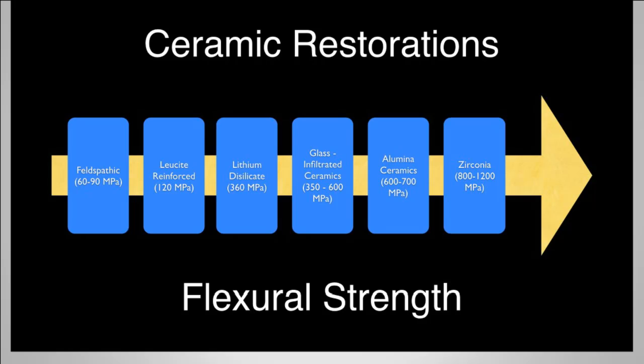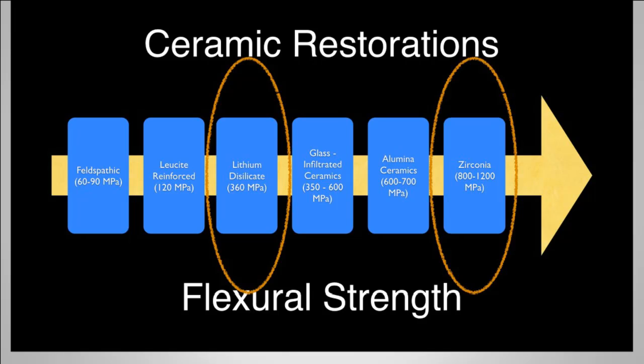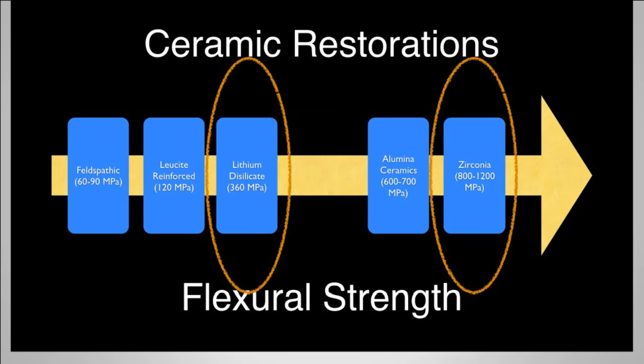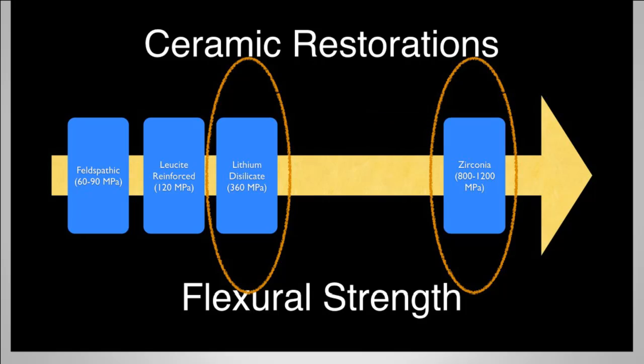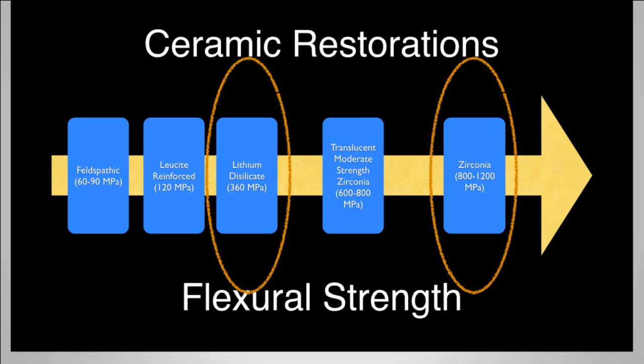In the newest area of dentistry, we're starting to gain more traction to this world of what we call translucent zirconias. So historically, it was this lithium disilicate area, as well as zirconia, and that's really been the last 10 or so years where these materials have really taken precedence. And today, we're starting to see things like Inceram and alumina go away. We don't really do many of those restorations today, and instead the world of translucent zirconias are starting to become more prevalent. And these translucent zirconias have a flexural strength of about 600 to 800 megapascals.